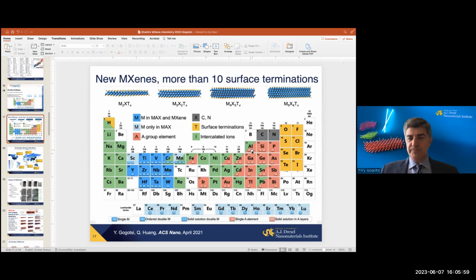7 years later, my other student, Mohamed Alhabeb, was able to etch silicon, because silicon you have to oxidize first. So you need to add an oxidizer to HF. So it's a slower process. You get more oxidized materials on the surface, which is sometimes desirable, sometimes not. We can etch gallium, but from two layers. For example, molybdenum carbide produced from Mo2Ga2C. And there is no good reason why, for example, thallium cannot be etched. But do you really want to work with extremely toxic thallium, where you can etch aluminum? So I would say it's a matter of preference.